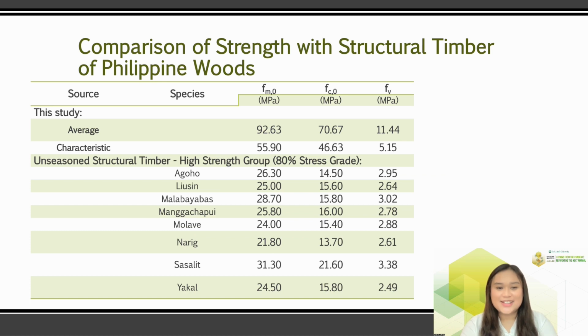The obtained strength values of Bambusa blumeana were compared to the reference values for visually stress-graded unseasoned structural timber of Philippine woods, considering the high strength group at 80% stress grade from the NSCP. It can be observed that all mechanical properties studied have far larger values than the indicated reference design capacities. This indicates that Bambusa blumeana is a viable alternative to wood as a construction material.